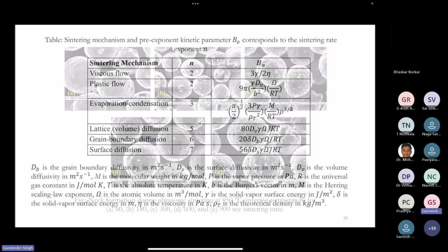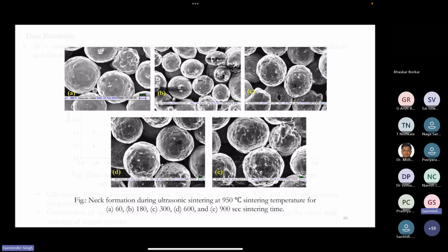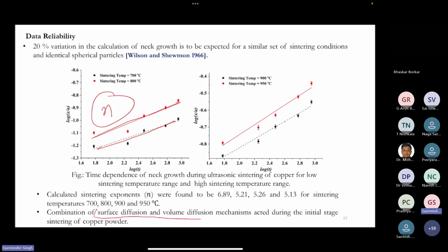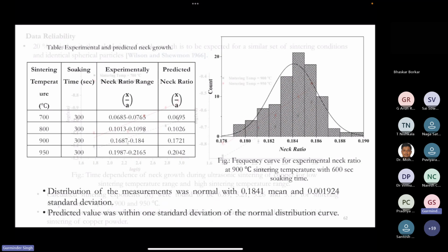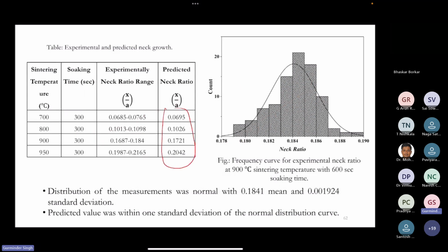For copper, we obtained that surface diffusion and volume diffusion mechanisms were the more effective, so that we can have a similar result with ultrasonic vibration sintering, in the experiments and also the prediction. Our predicted neck ratio value was in the range of the experimental neck range value, and it has a uniform distribution also.